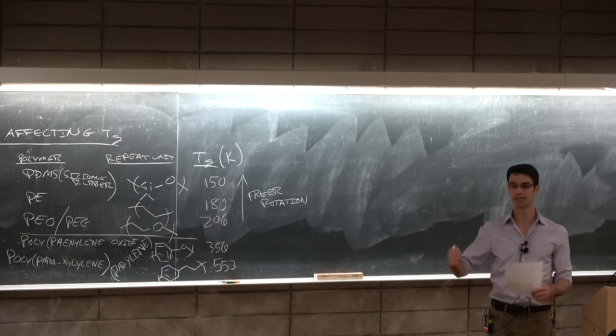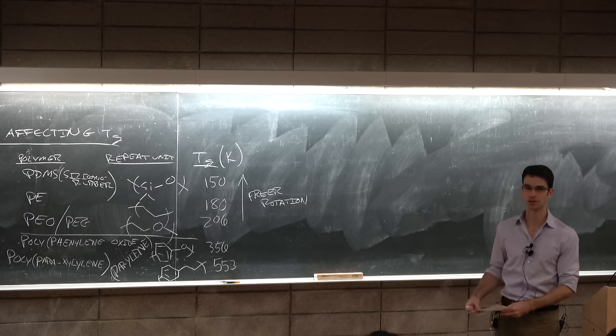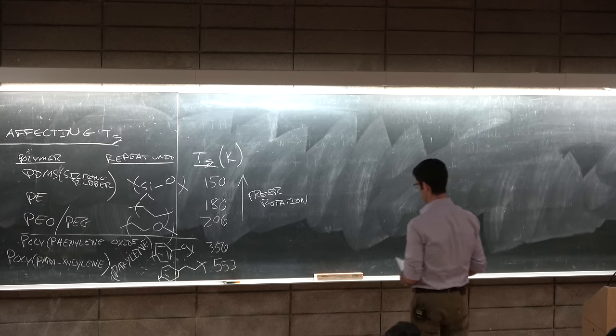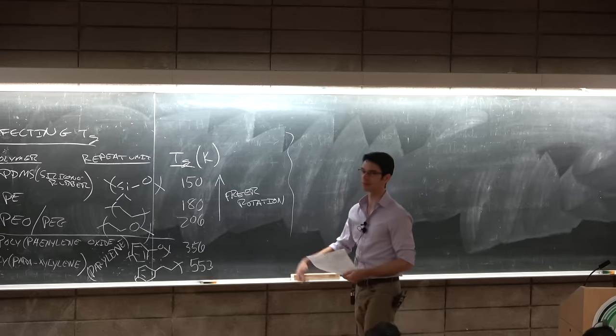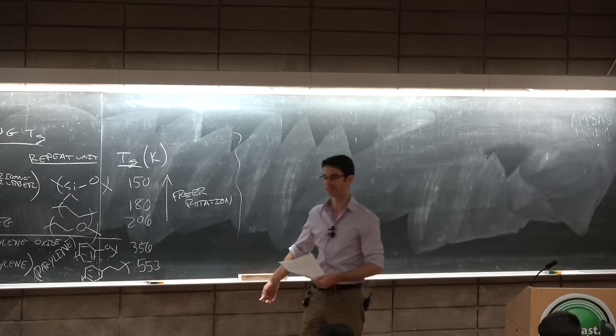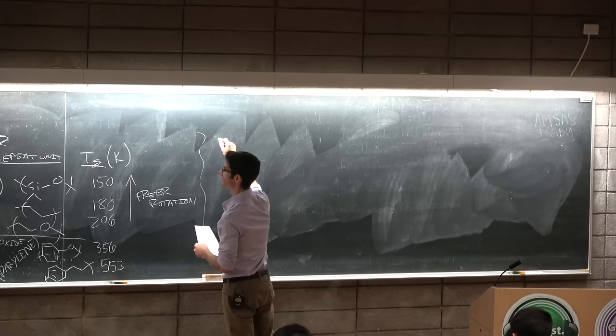This is called parylene. And parylene has the structure of benzene rings linked by ethylene, by an ethylene unit. And this has a very high TG which is what makes it a good material for electronics packaging, of 553 kelvin.